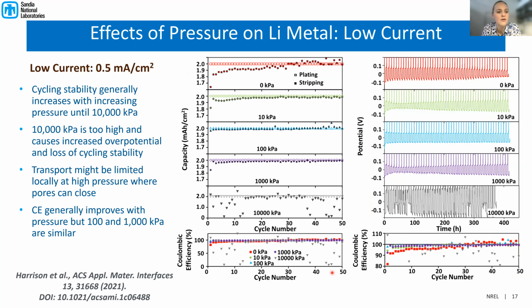Okay, this is what was found. So for low current, with the effects of pressure going from 0 kilopascals, 10, 100, 1,000, and 10,000, you can see that there's actually an improvement in the capacity as you're going from 0 up to 1,000 kPa. But then as you get to 10,000, there's a bit too much pressure, where we're thinking that that's causing an increased overpotential and some transport issues, likely because the separator in between the electrodes is being compressed too much, and the pores are restricting the electrolyte from moving between the electrodes. And so we see that there is kind of an optimal range for getting better performance of the lithium for plating and stripping.